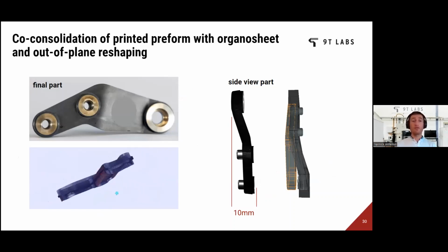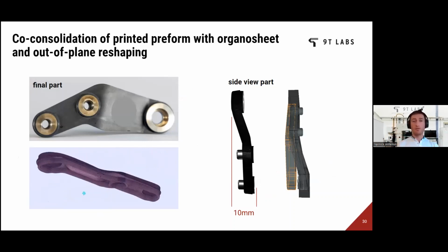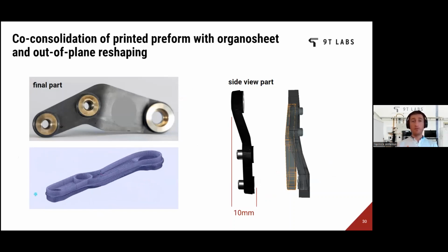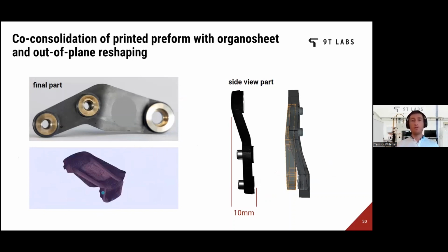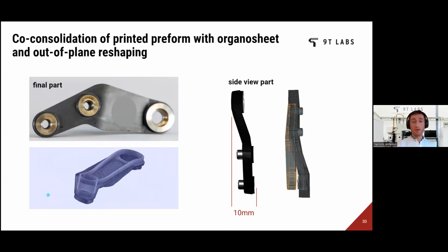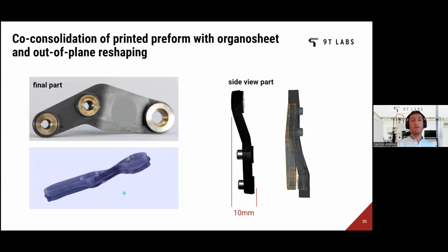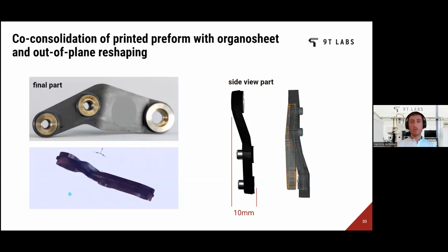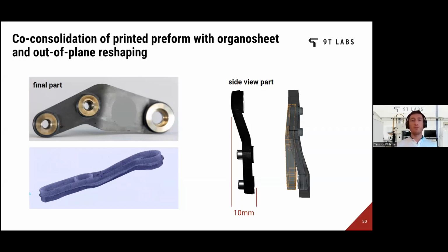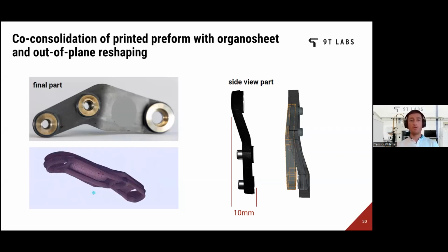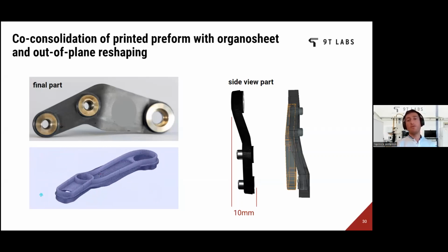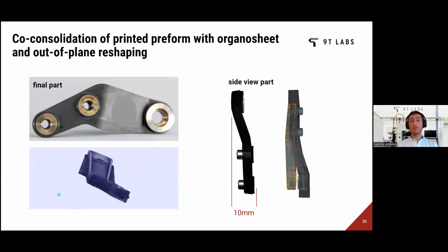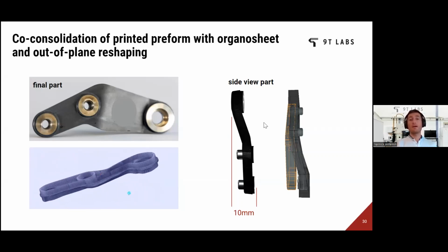So that's also what is very interesting when we develop the final part in the digital environment. We can project from 2D to 3D and already, of course, take into consideration how to place the fiber for the final reshaped part, because this obviously will create some inner stresses, and we have to know about it in order to already decrease these potential inner stresses, which will either way be able to kind of cure out of the part in the post process. And you see actually here we have very interesting parts. So we go from flat, we reshape it by quite a bit. I mean, you see it's bent on the right side.